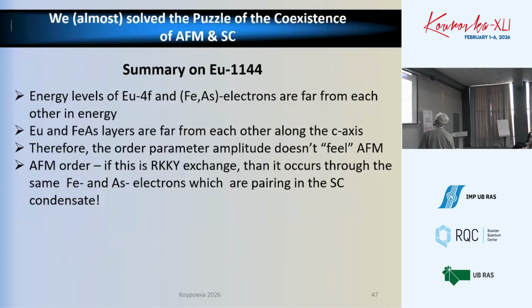Now, just a summary of what I have shown: the energy levels of the europium 4f electrons, which are responsible for magnetism, are far away from each other in energy by 1.8 electron volts. And in real space, they're also far away from each other because the crystal is layered. Therefore, the order parameter amplitude maybe doesn't feel the antiferromagnetic ordering. But on the other hand, these arguments do not entirely address the issue.